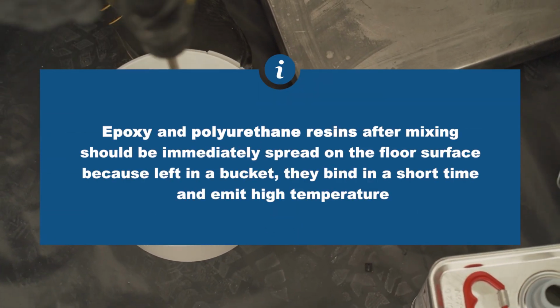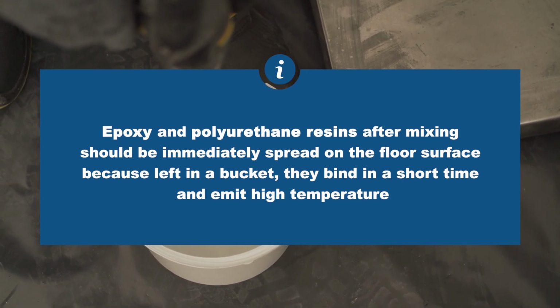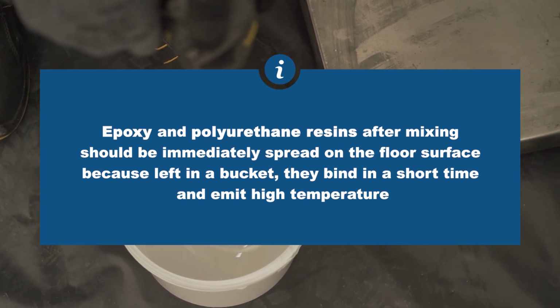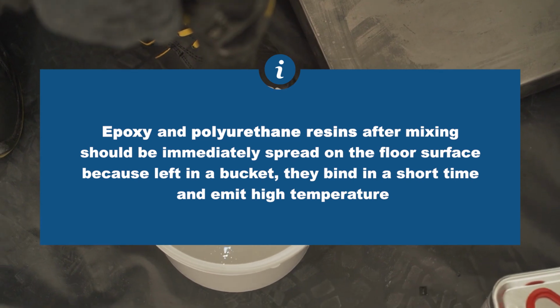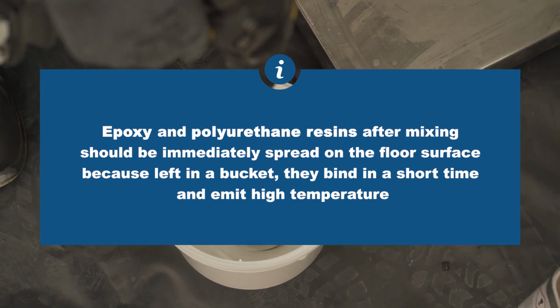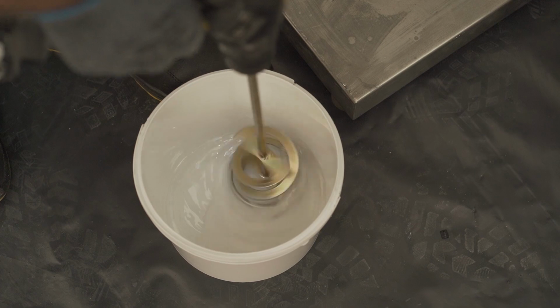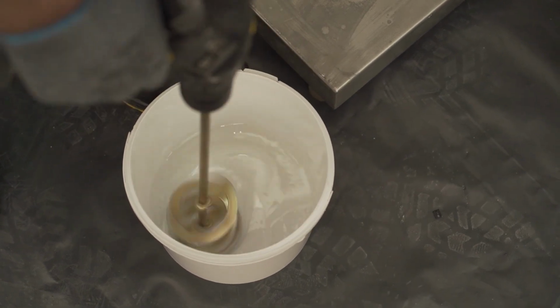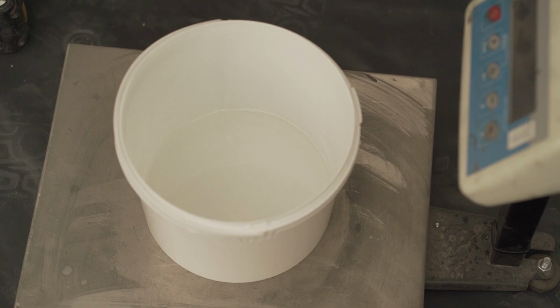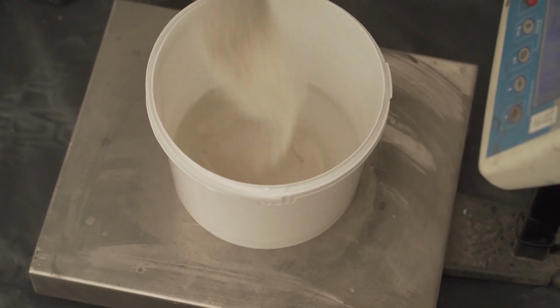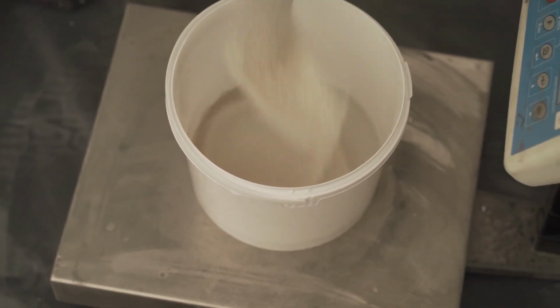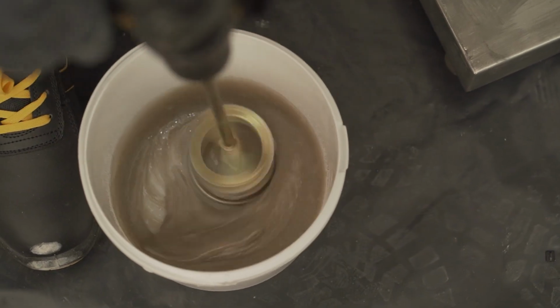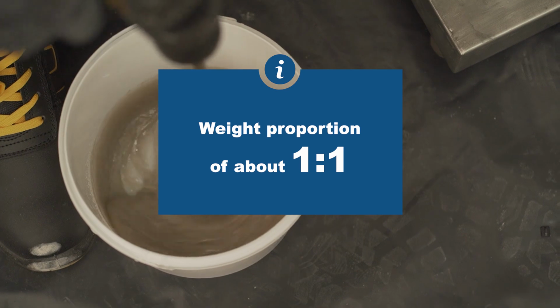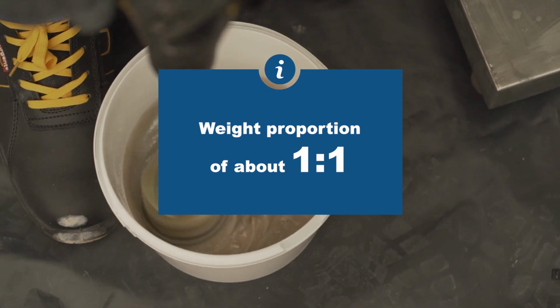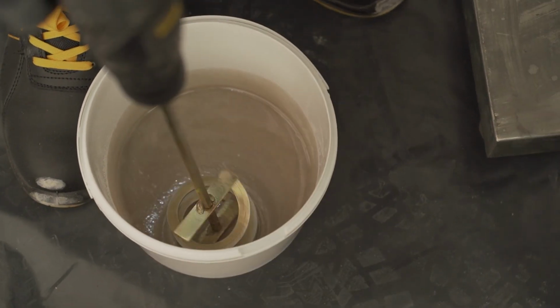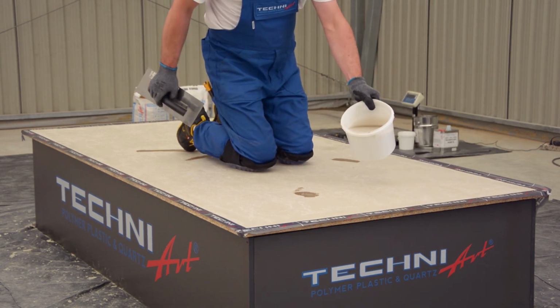Epoxy and polyurethane resins after mixing should be immediately spread on the floor surface, because left in a bucket, they bind in a short time, and emit high temperature. To the previously mixed TechniArt 400 RST ingredients, add quartz sand with granulation from 0.1 to 0.4 mm, until the consistency of an easily pourable mass is obtained. Most often it is in a weight proportion of about 1:1. And it depends, as before, on the ambient temperature in such a way that the colder, the less sand in the mixture.